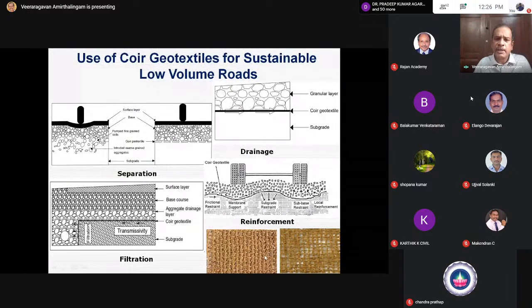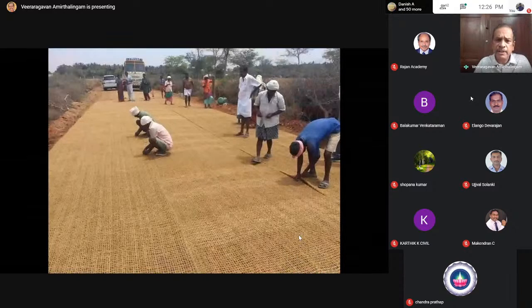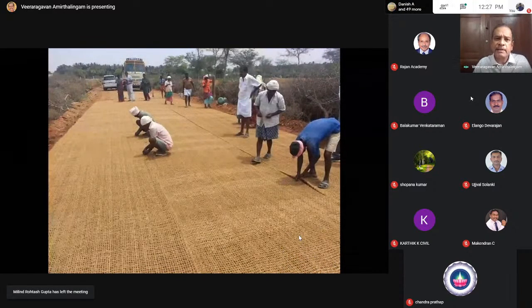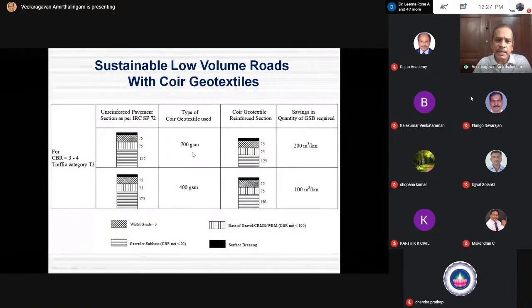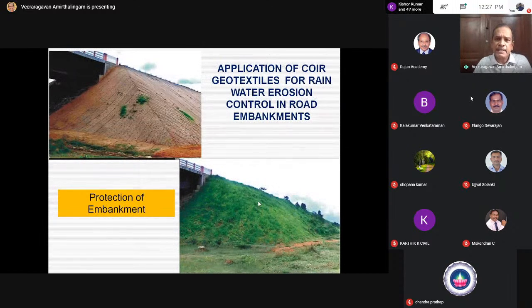There are two different types of coir available, different GSMs. For a rural road, we constructed with a coir, and we found that if you can have 700 GSM or 400 GSM, you can bring down the thicknesses, say 175 plus 150 to 125 plus 150. So I can bring down the thickness by 50 millimeter here. I can bring down from 175 to 150 here. So it is possible to ensure sustainability in low volume roads using coir. You can also use jute also. Other applications are water erosion control using coir. Grass will grow. You may ask me a question. Will it not be biodegradable? Yes, they are biodegradable.